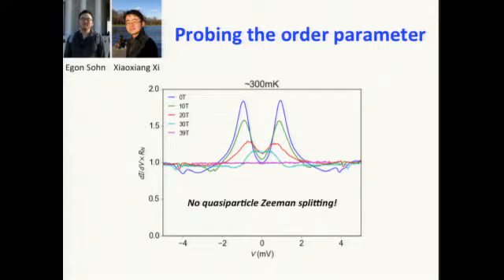As we increase the magnetic field, the first thing I want you to notice is that there's no Zeeman splitting in the quasi-particle peaks, which is completely different from a BCS superconductor. This supports the picture that the spins of the quasi-particles are locked to the out-of-plane direction by the spin-orbit interaction. Secondly, you can see that the gaps are continuously closing with increasing magnetic field.